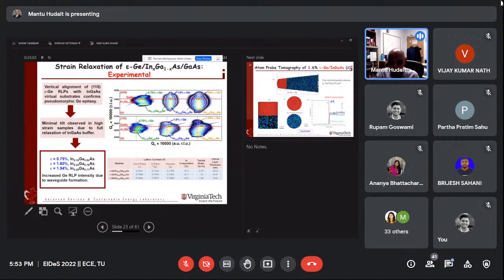So we were kind of stuck on that. Please remember that the interface has to be abrupt. No interdiffusion means no germanium goes here or arsenic goes here. If any goes there, that has to be really minimal. But how minimal is minimal, right? Is it 1 nanometer, 2 nanometer, 10 nanometer, 100 nanometer? How much is it? See, this kid is stuck pretty much.